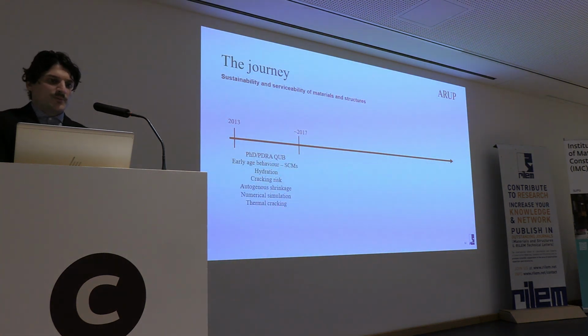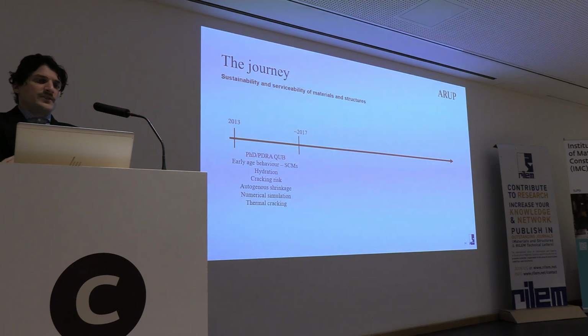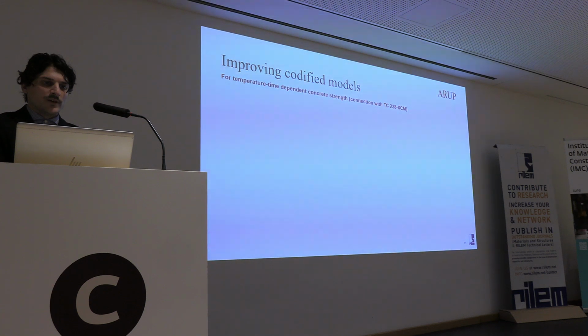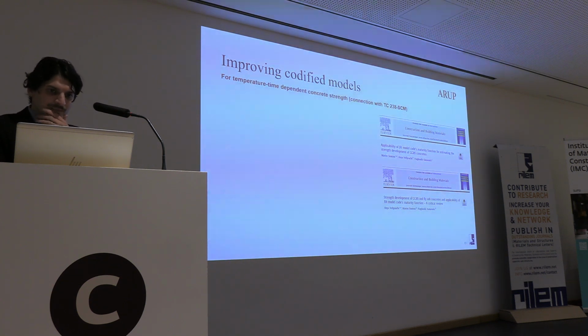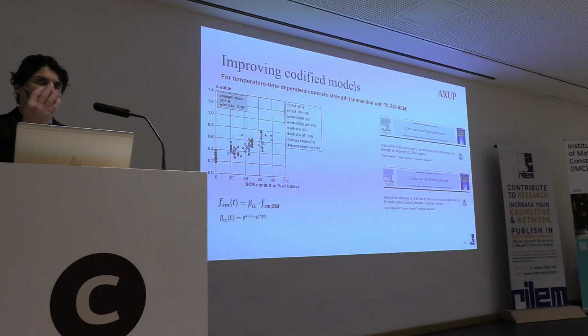But towards the end of that part of the journey, two quite career-defining occurrences took place. One was my introduction to some members of the TC 238 on supplementary cementitious materials that the current RILEM president was actually chairing, and that was working on improving codified models from some of the members of this TC. And we particularly focused on the fib models and how we can improve those, because these types of models for strengthening are used throughout the industry, but are not providing adequate provisions for supplementary cementitious materials such as slags and fly ashes and other ternary blends.